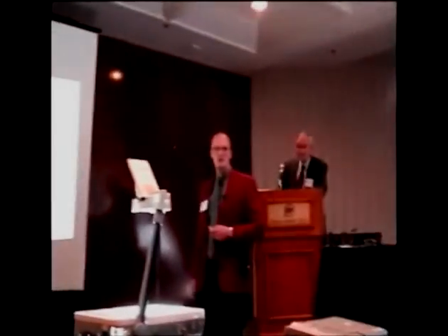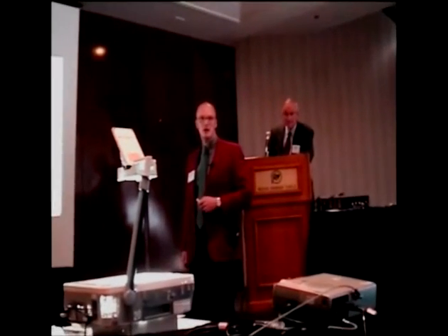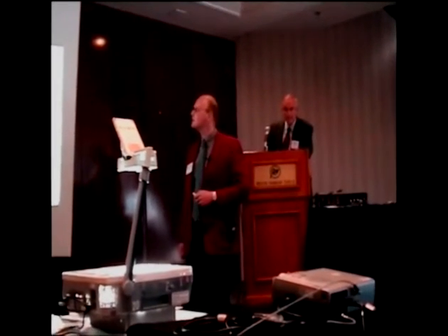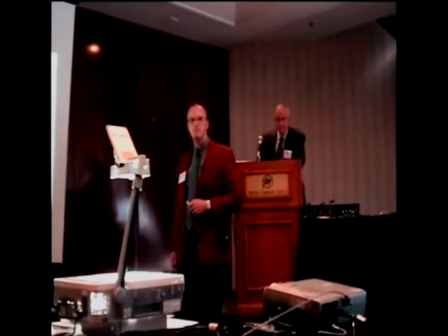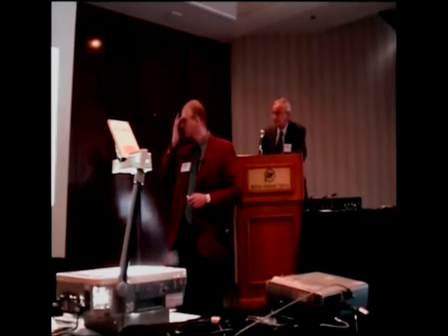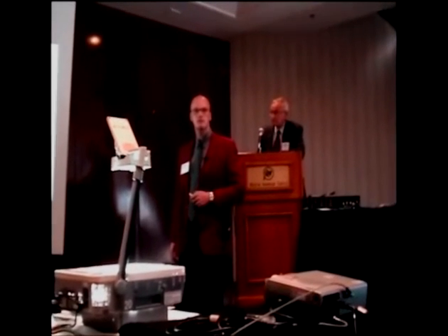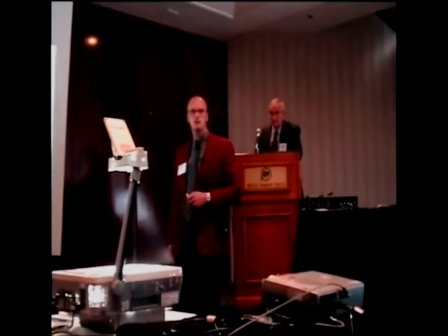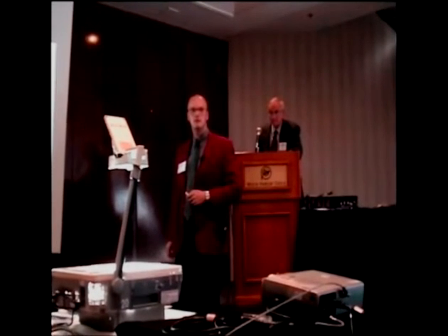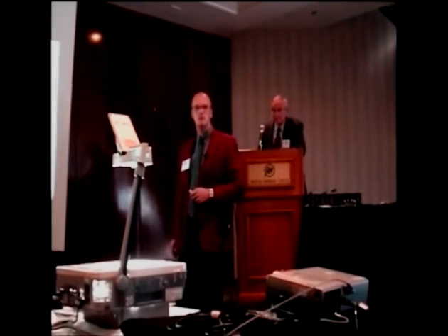So you seem to have about the same rates of HDS and hydrogenation for both systems. For the molybdenum catalyst only, you have a ratio of about 7 times HDS to hydrogenation. In the other two cases, you have almost a similar ratio. It doesn't seem to fit the idea of increasing the number of vacancies.